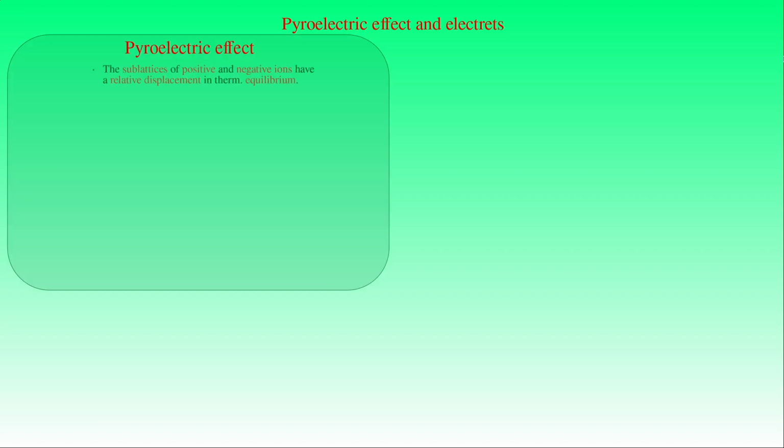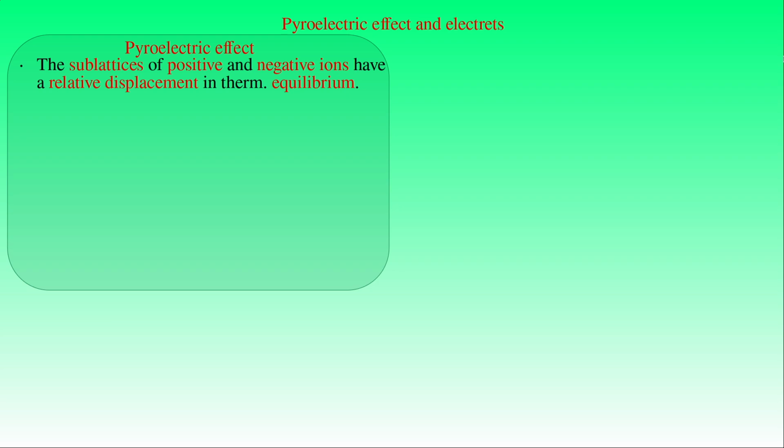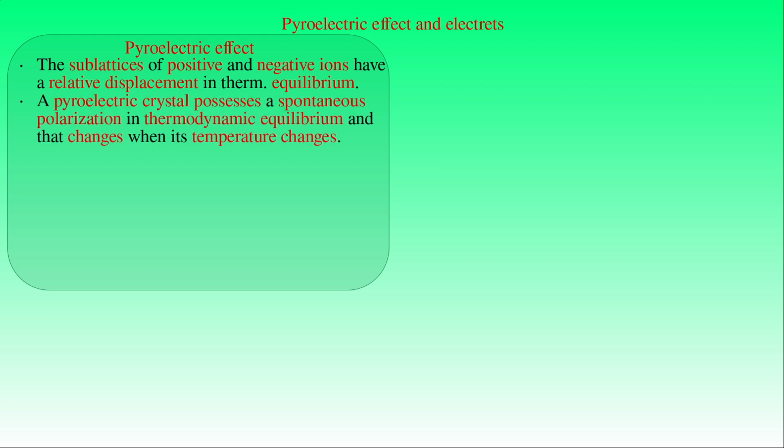In certain piezoelectric crystals, the sublattices of positive and negative ions are displaced relative to one another in thermodynamic equilibrium, resulting in an electric polarization even in the absence of an external electric field. Piezoelectric crystals that exhibit such spontaneous polarization are called pyroelectric crystals. In other words, a pyroelectric crystal is a crystal that possesses a spontaneous electric polarization in thermodynamic equilibrium and whose polarization changes when its temperature changes.